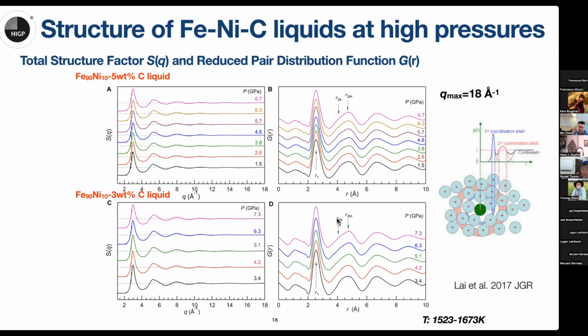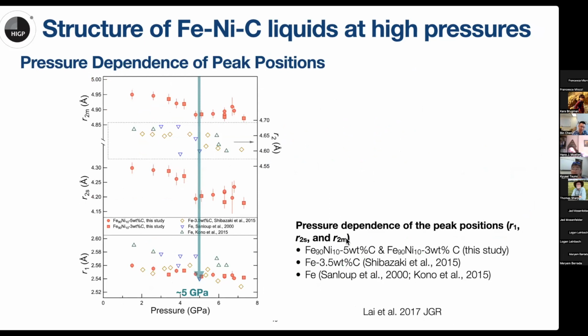As we can see from the PDF, the second shell has a main peak and a satellite peak. So we performed a spectral analysis of the peak position of the second shell peak. We found that at about 5 GPa, there's a substantial reduction in the second shell R value, the position. This is indicative of a pressure-induced liquid structure transition in this liquid.